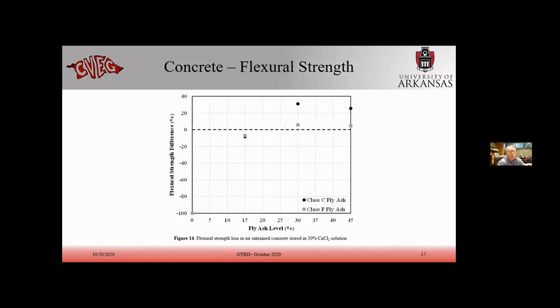The flexural strength, that was our modulus of rupture, our measure of tensile strength. Once again, the cement-only mixtures couldn't be tested. The other ones, we didn't really see as much difference, but you know, it's tensile strength. For those of you who've done tensile, I think our tensile strength is about 800 PSI. So there is some variability in just the test results.